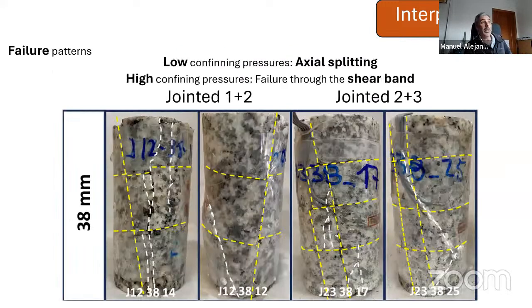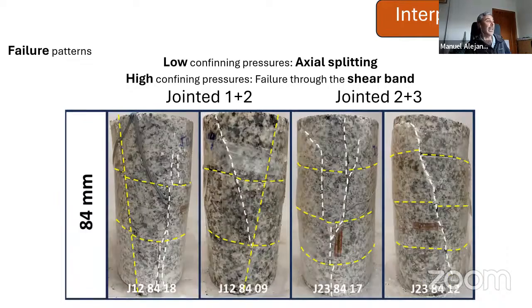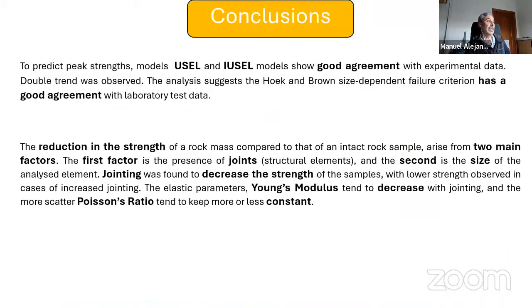Moving on to the failure patterns, we can see the same patterns obtained in the intact ones: at low confining pressures we have obtained axial splitting, moving to a shear band for high confining pressures. And we have found this for all the different sizes.